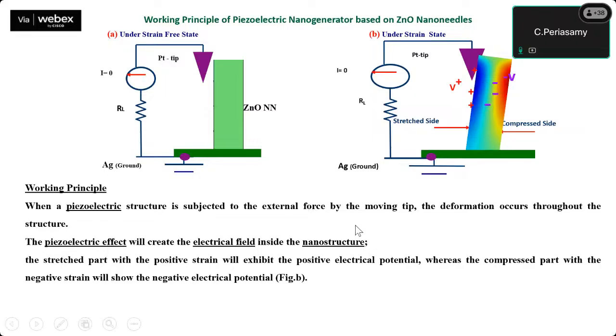nanostructure. Please note that here we are not applying any bias across this nanostructure. We have considered a single zinc oxide nano needle to demonstrate the energy harvesting application. How will this single nano needle convert mechanical to electrical energy? While scanning with the AFM tip, for example from left to right, as the tip deforms the nanostructure, the stretched side will generate positive potential, and the compressed side will generate negative potential.